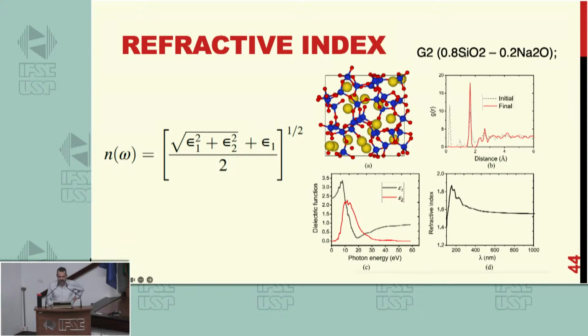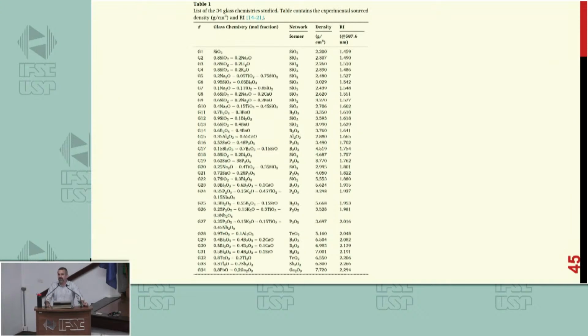This is just a very simple glass, 20% of sodium and 80% of silicon. And then at the end, you are going to get some result like this, where you have the refractive index as a function of wavelength, okay? Here you have a snapshot of the crystal structure and so on. So what calls my attention about this paper is the following, why I liked it. It's very robust, the methodology is very good, and they did a lot of calculations, but I looked for other papers from them and couldn't find something. You know when you are ready to do something much bigger with the results you have, and they have not published. Probably the company has all this cool information that you could get from this, but it's just not published. You know, they hold them for themselves.